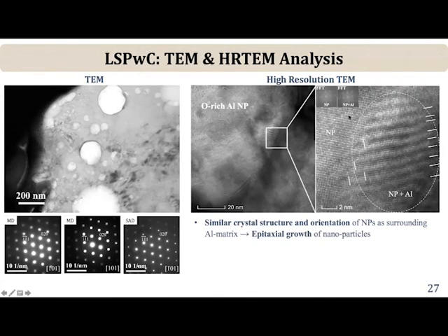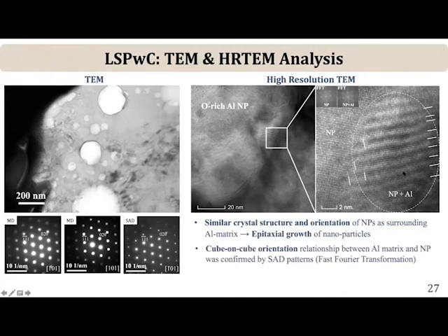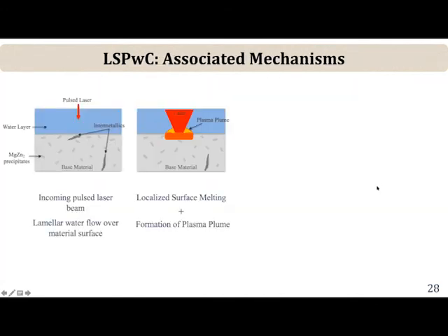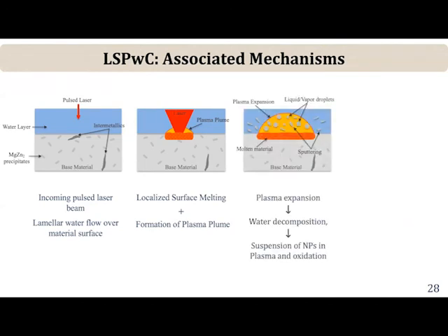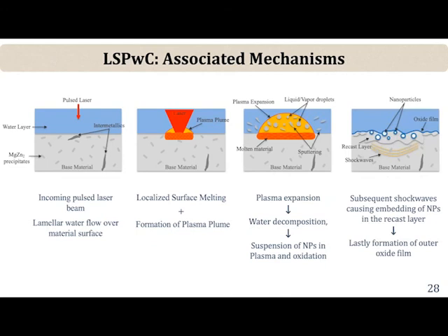But the interesting thing is there is a one-to-one correspondence of these particles with the surrounding matrix. So even though this plume has formed and then collapsed, the aluminum particles almost epitaxially solidify with the surrounding matrix, which is very interesting. And a little bit of that mismatch is taken up by misfit dislocations at the surface. This is a very interesting thing that we have observed, and this work was published in Scripta Materialia, and we have submitted another paper to Materialia. So this gives you some idea about how we think this near surface microstructure is forming, but I don't have a whole lot of time.